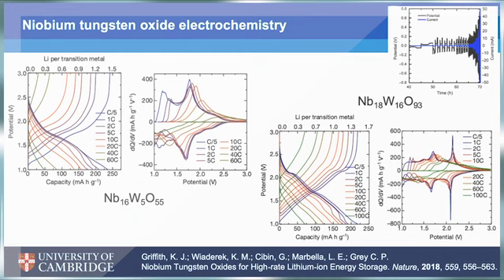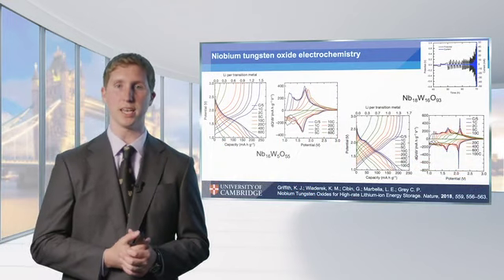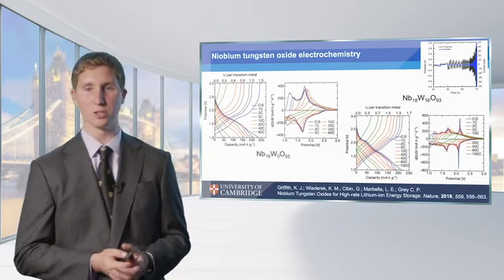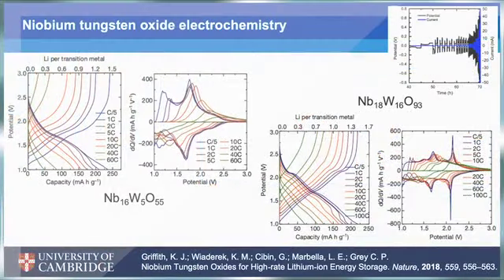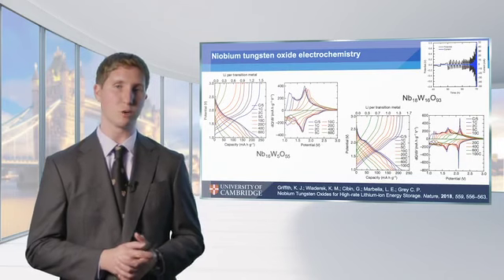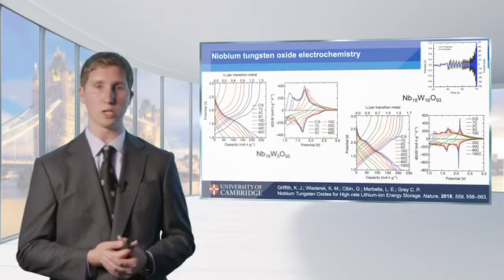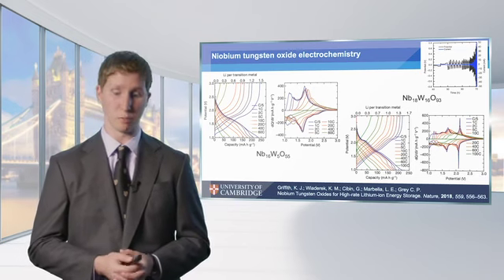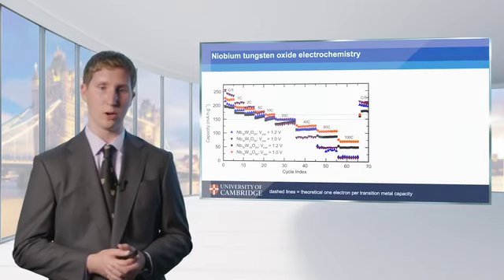So these niobium tungsten oxides were tested in half cells against lithium metal. So we wanted to see what the effect of the lithium metal was, because you can't truly independently test a single electrode. And so we made lithium-lithium half cells, which is this plot that I've superimposed in the top right here. And what we observed was that at the current densities that correspond to our high rate measurements, say 10C, 20C, we saw an identical overpotential in the lithium-lithium half cells. So we believe that overpotential is coming from something in the process of lithium plating and stripping and the associated ion transfer for those reactions. And so actually we're not necessarily pushing or observing the limits of our NWO materials. We're observing the limits of a cell as a whole, and these could well be coming from the lithium metal process.